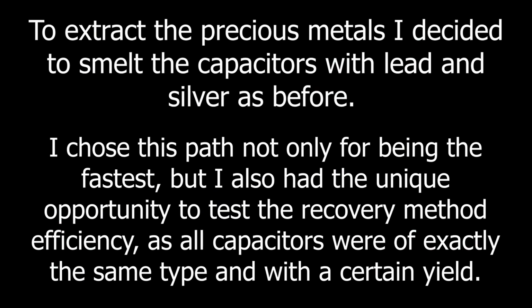To extract the precious metals, I decided to smelt the capacitors with lead and silver as before. I chose this path not only for being the fastest, but I also had the unique opportunity to test the recovery method efficiency, as all capacitors were of exactly the same type and with a certain yield.